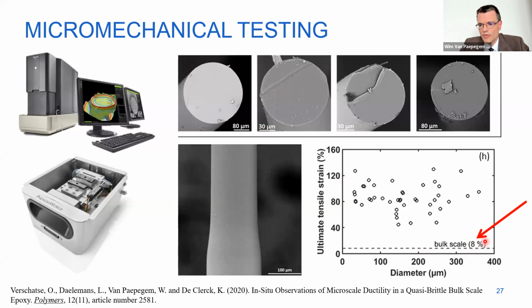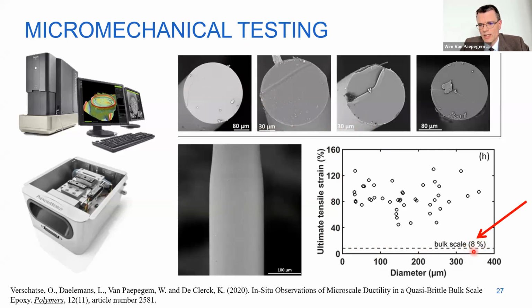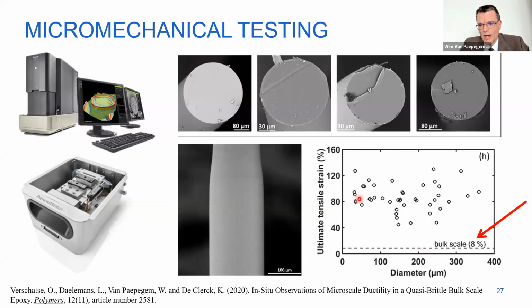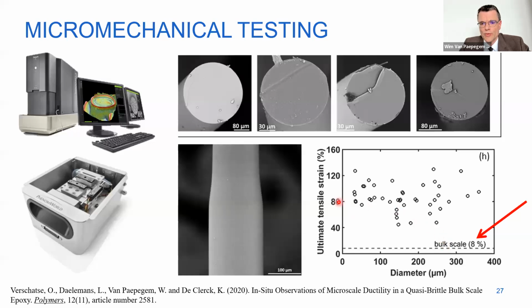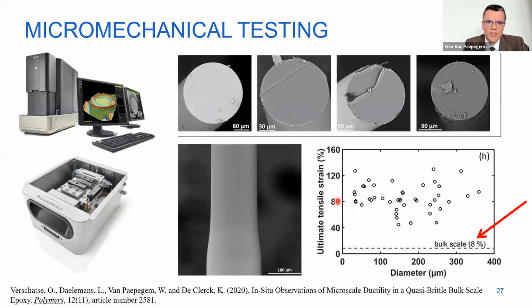And here is the failure strain of the bulk epoxy, just a coupon scale. And you see, I admit there is a lot of scatter and we don't manage to make it smaller, but on average, the failure strain is much, much higher than the bulk. And also the strength is much higher. So we do see some indication that maybe there is a size effect there.